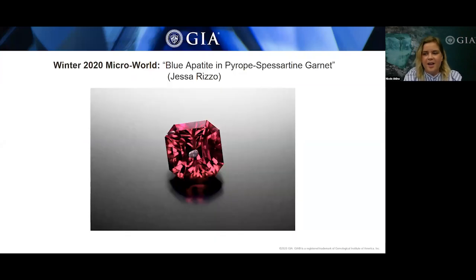Here we have a 5.33 carat red pyrope garnet, which is reportedly from Madagascar. This author picked this rough for an eye-visible blue apatite inclusion just below the rough surface. They then prepped and cut the stone to orient that blue apatite crystal to be on full display through the table of the finished cornered mixed cut, as you can see in this photo.